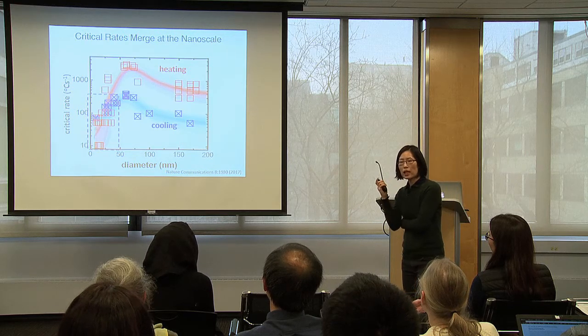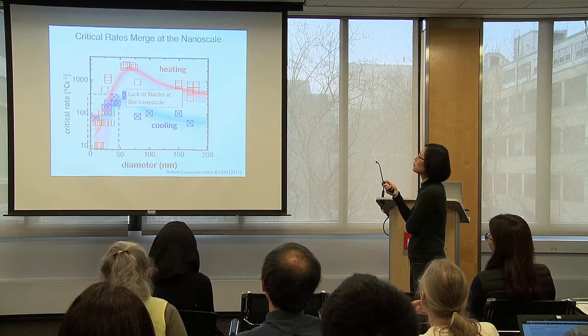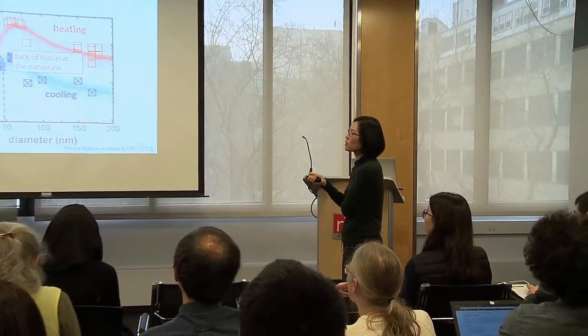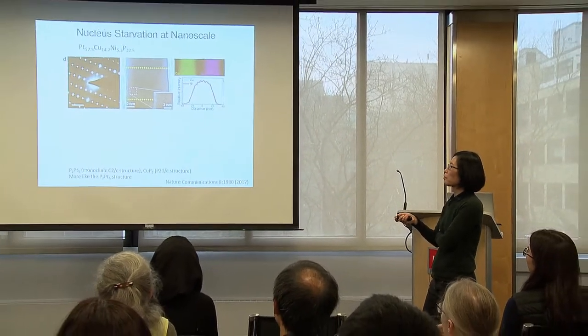This can still be explained by classical nucleation theory, simply for the fact that in small rods, you simply don't have that many nuclei. If you don't have that many nuclei, it doesn't matter where this window happens, because you just don't have that nuclei. Thereby, the kinetics should be similar for both heating and cooling. Okay? Now, the fact that you don't have that many nuclei actually is a way to create metastable, novel crystalline phases. This is a multi-component metallic alloy. If you crystallize this in bulk scale, it's going to form thermodynamically stable binary phases.